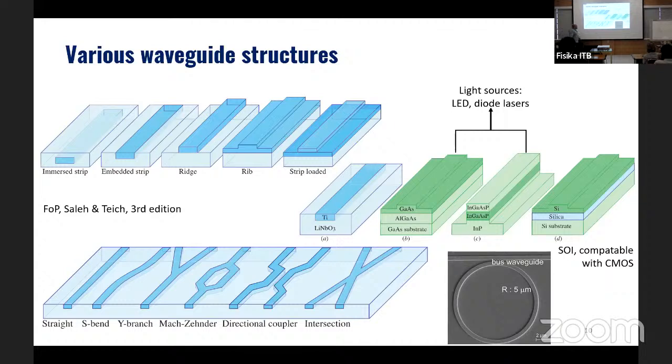If you want to make silicon waveguide with a certain kind of losses, yeah, okay, then you got some problem, right? So this is just showing a certain kind of flavor of optical waveguides that have been used. Somebody asked the question online yesterday about lithium niobate, great material, but typically you have lithium niobate with very big mode area and weakly guiding. Why? Because it's very difficult to structure lithium niobate. So the way you make a waveguide is you diffuse titanium to slightly change the refractive index locally for lithium niobate, such that light can be channeled, can be waveguided. But then the index contrast is pretty low.